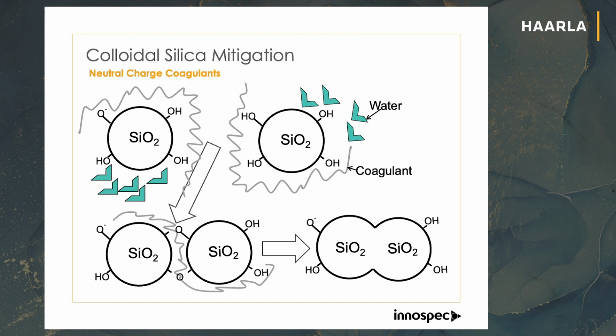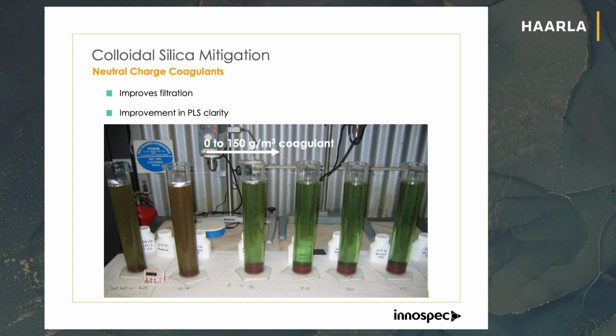That is the mechanism we want to promote to get this as effective as possible. Now, you will see this in two different parts of the process. If you are looking at the filtration area, on the left-hand side of the cell you can see no additive is in there, and you can see what it looks like. It's quite difficult to filter. As you then increase the coagulant, you can see you're getting a better separation, which means it's a lot easier to filter. It goes through your process a lot better. You get a purer product.